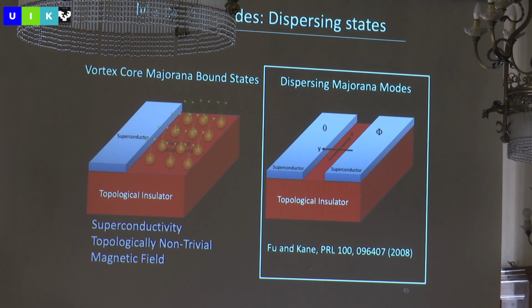And so you shouldn't really see a zero bias state. The Caroli-de Gennes-Matricon states are always separated from the Fermi energy by some energy. And so the existence of that zero bias state, as well as, I haven't shown you this data, you can actually see in certain vortex cores there are also other additional states which have the same Majorana character that are separated from the zero bias state by a different integer spacing.